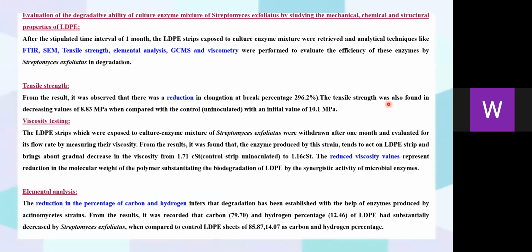The evaluation of degradability of the culture enzyme mixture of Streptomyces exfoliatus by mechanical, chemical, and structural properties. Tensile strength: it was found that there was a reduction in elongation at break. Tensile strength was also found to be decreased to 8.83 MPa when compared with control.